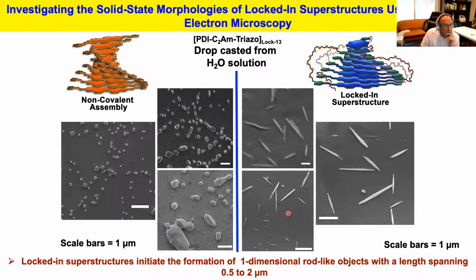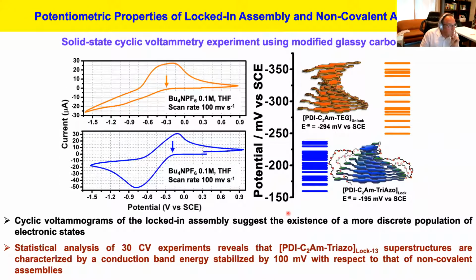Okay, so now what can we do with these materials, right? Again, these materials can be solvated in methanol, THF, water, while still maintaining their electronic structure. And so what we have done is really classic cyclic voltammetry experiments, where we have taken this solution of non-covalent assemblies and locked-in superstructures, and we have drop-casted them onto glassy carbon electrodes. And so the question that we were interested in is: can we modulate to some extent the conduction band energy of each of these assemblies? And so each of these data points that I'm showing you with my laser here are the result of different measurements.